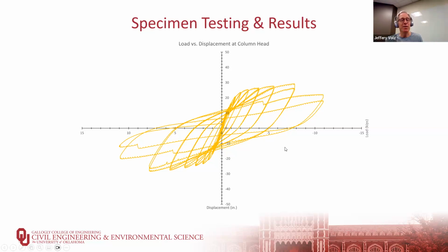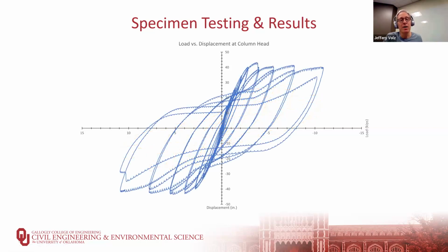So we felt very comfortable that our test frame and our test protocol was indeed doing the things that we needed it to do. So then we moved on to the SCC column, shown in this next load displacement plot. Now you can see here, as we did with the reinforced concrete column, you get a linear elastic response. The steel tube and the concrete are acting nice and linear elastically. At some point, we're not sure, you're going to debond that concrete core from the base. We're also starting to get some nonlinear behavior.